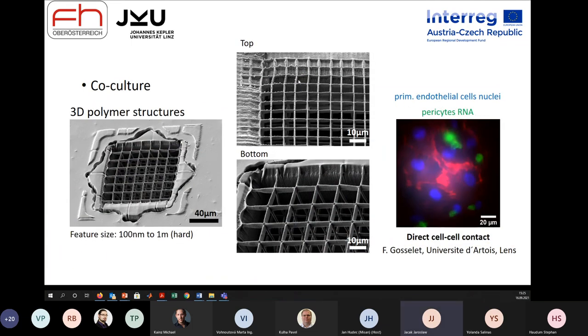So this is how our structure looks like that we demonstrated for the co-culture, which means we had a first layer of cells which has been seeded. Then we waited for 3 hours just to let the cells land on top of this. You see the different periodicities. Here is the low periodicity, here is the high periodicity. This is where the cells can enter. Here the cells cannot pass through. You nicely see the red and blue colored cells are the cells on top, and they form nice junctions. The red colors are the tight junctions, which means these endothelial cells are very closely connected, so they basically form a barrier. And the green ones are pericytes.